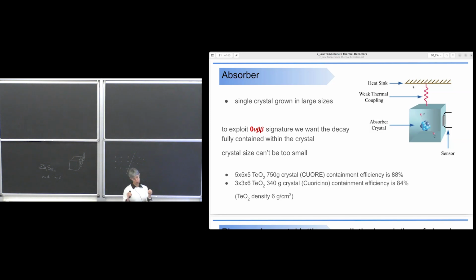Keep in mind that each crystal is an independent detector with its own sensor, its own readout chain. So 10 to the 6 channels are not acceptable for a cryostat. We want the decay fully contained inside a crystal in order to have all the energy deposition inside it. Therefore, the crystal size can't be too small. This is an additional motivation to keep the crystal size as large as possible.